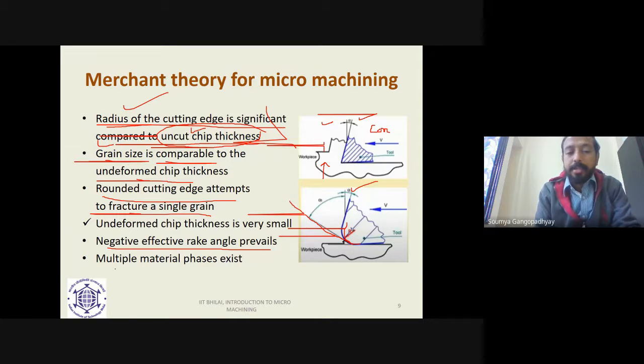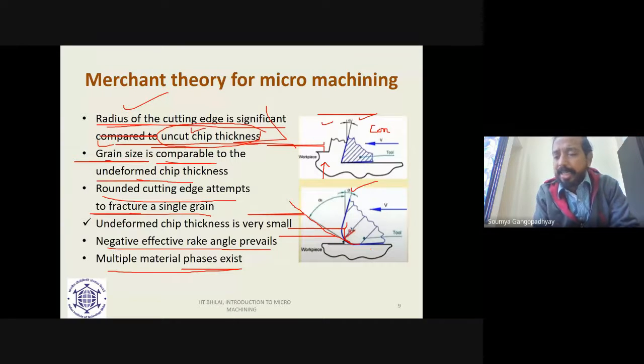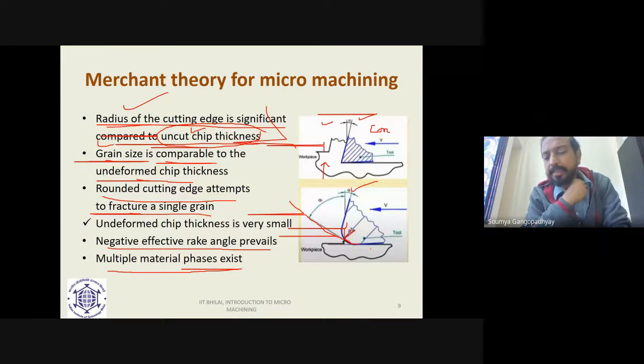And then multiple material phases exist because the workpiece actually consists of different phases. It is ultimately an alloy, and therefore there are different phases present, right? Pearlitic, if you are considering steel, martensitic phase, pearlite phase, ferritic phase, etc. exist at different locations. If you are considering Inconel, then gamma prime phases exist. So different phases exist even in a single material at a very micro scale. But when you are doing macro machining, microscopic inhomogeneity present in the workpiece gets nullified. But in micro machining, this microscopic inhomogeneity becomes highly amplified, making it a challenge. And then the specific cutting force increases, the specific cutting energy increases.